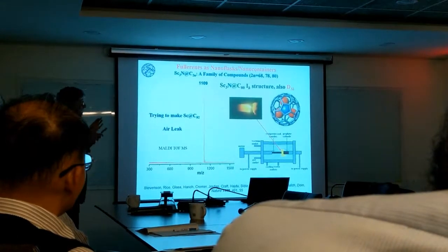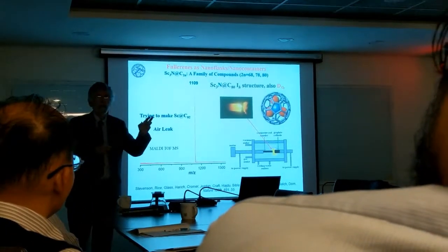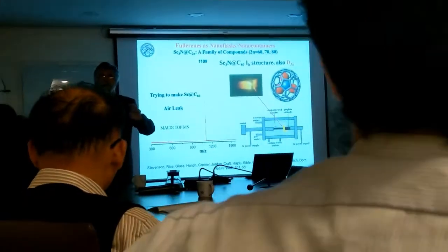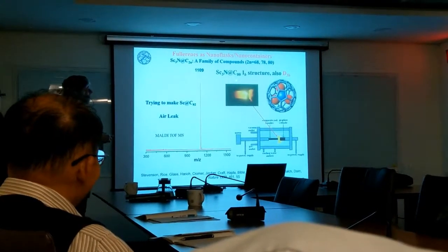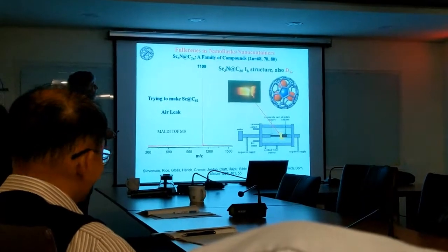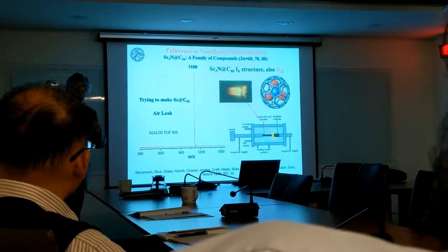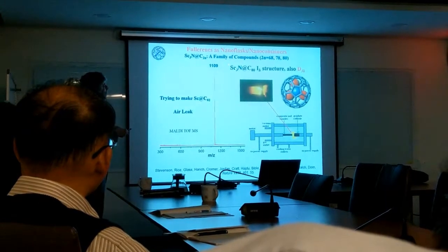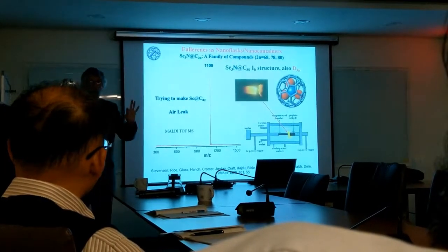Okay? And the nice thing about this is, who is the best inorganic chemist here? Nobody can prepare scandium nitride. Okay? Scandium nitride does not exist. Not even the best inorganic chemist here. Okay? Who is the best organic or fullerene chemist here? Well, icosahedral symmetry C80 or D5h C80 do not exist empty. Okay? They have been detected, but you cannot isolate C80 icosahedral symmetry or D5h. However, this one inside of this is the third most abundant fullerene that can be prepared.